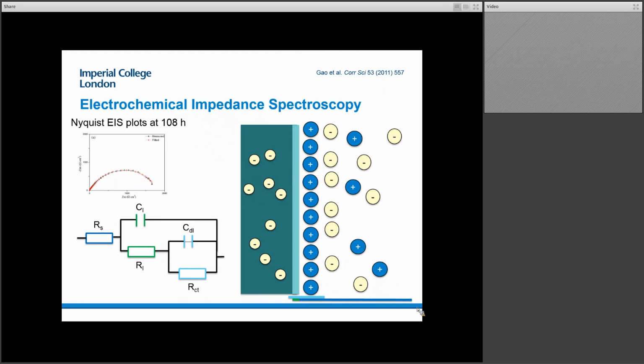And one of the difficulties at this stage can be that with a non-ideal system, the match may not be as ideal as one would hope, right? So you calculate something like the least squares, and you find that in fact the compatibility may not be exactly where it is. But one of the things that often comes up is that you may have gone to a frequency that is so low that in fact your system started to become dynamic. You verged too far from steady state. For example, as one of the challenges that comes with corrosion and impedance.